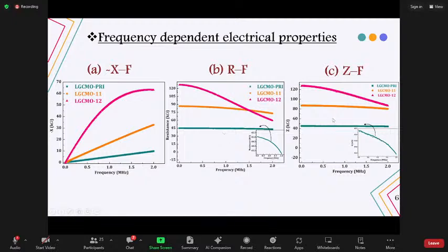Graph C shows the impedance versus frequency. From this graph, we can see that the value of the impedance decreases with respect to applied frequency, and in the lower frequency region the impedance value is higher. That is due to the accumulation of charge carriers at the lower frequency region. The overall value of the impedance increases upon irradiation. That is due to the defects and the strain due to higher fluence.